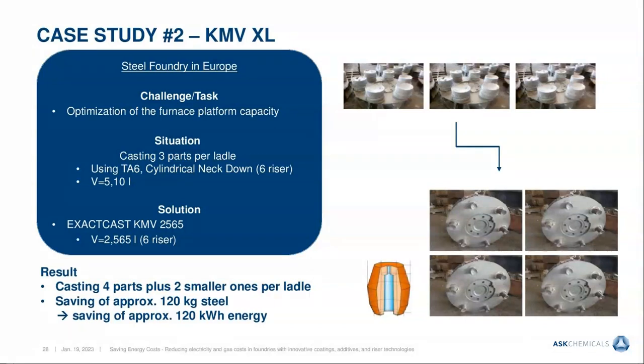And the good thing for this customer was that with the same ladle, he was able to pour one more casting of this regular one plus 2 small ones. So the furnace capacity was really optimized. And in the end, again, the energy savings were also about 120 kilowatt-hours.